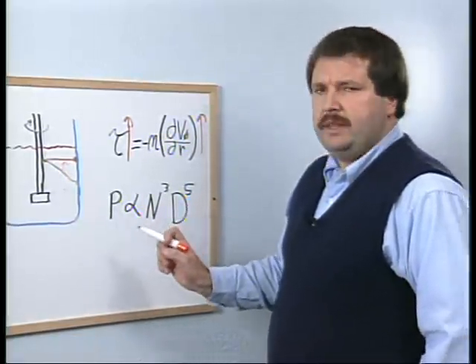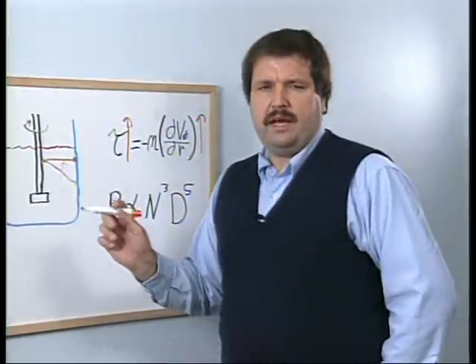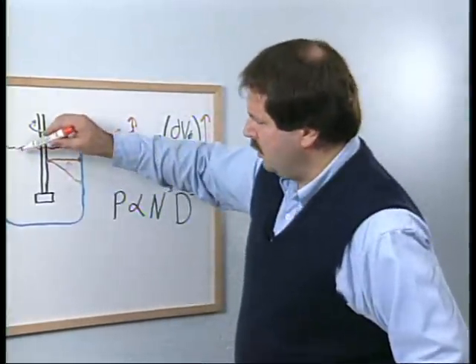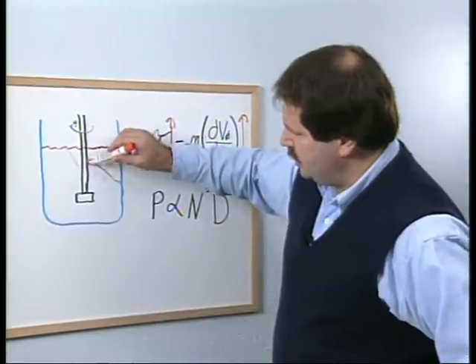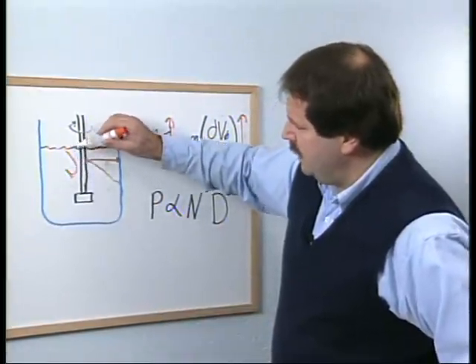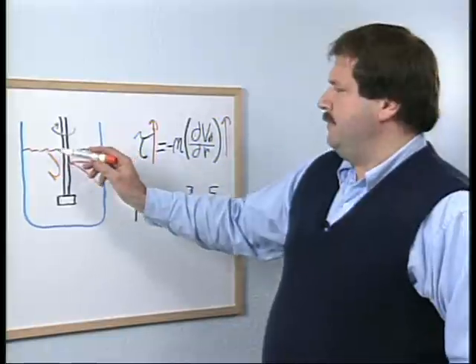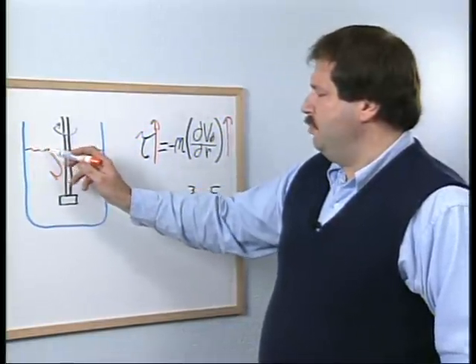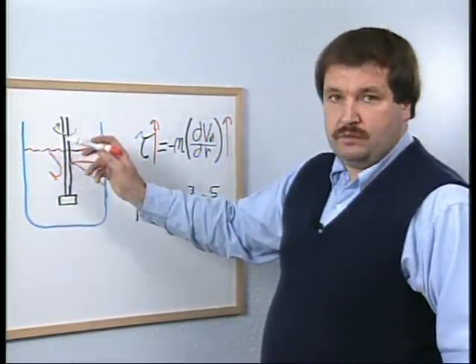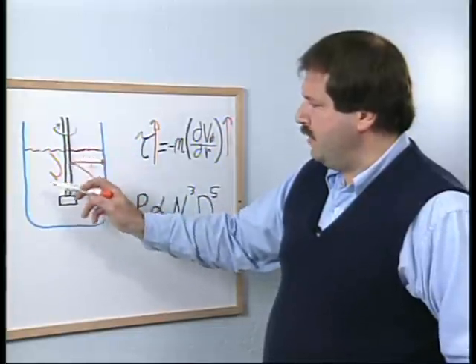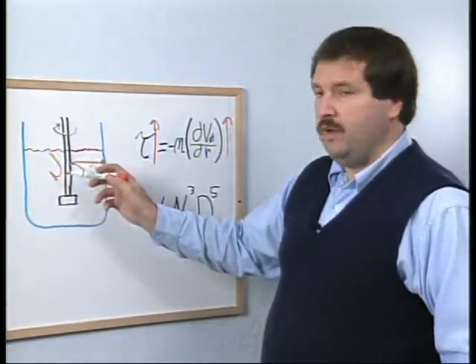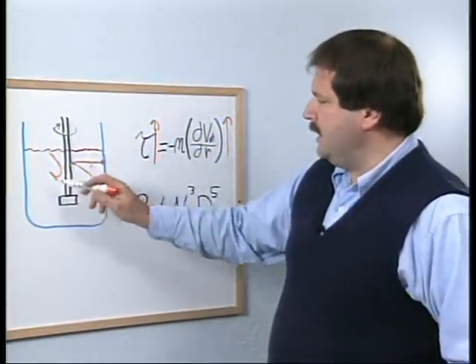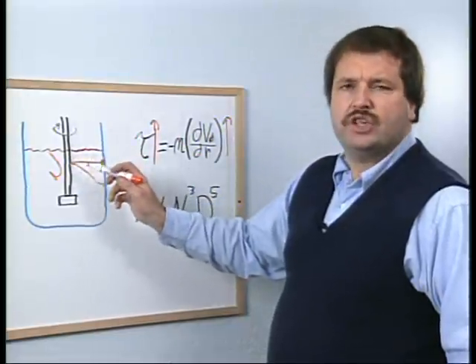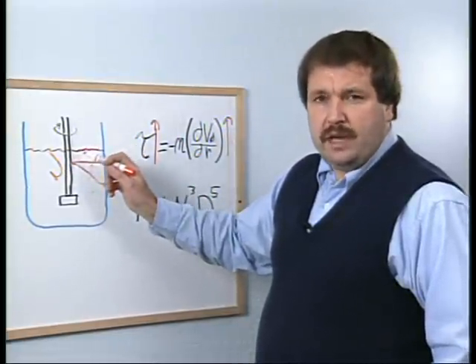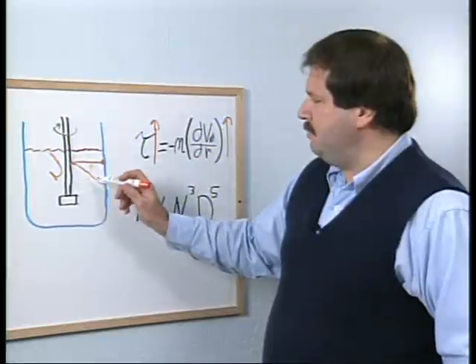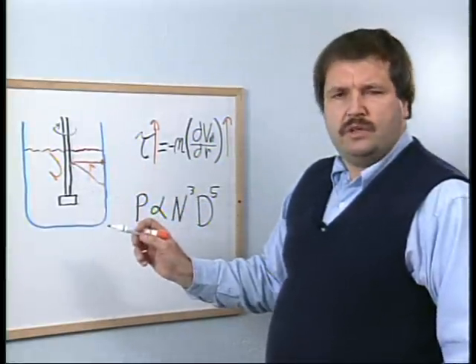The problem with doing that in a conventional process is that vorticity begins to occur, and we see a surface depression that's represented by a rolling of metal and the advection of supernate that is transported to the surface as a result of the fluxing process, and an entrainment of that surface material in the melt, very undesirable. And secondly, metal begins to rotate in a reaction vessel to the same velocity ultimately as the rotating impeller, that in turn relaxes the velocity gradient.